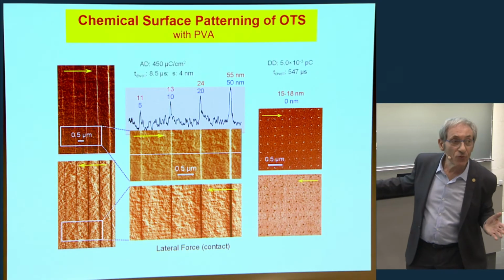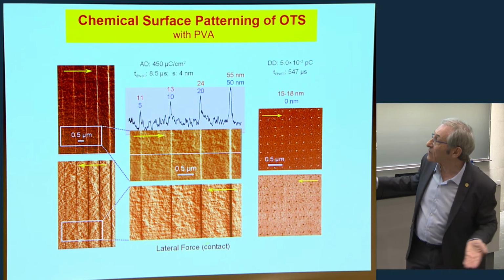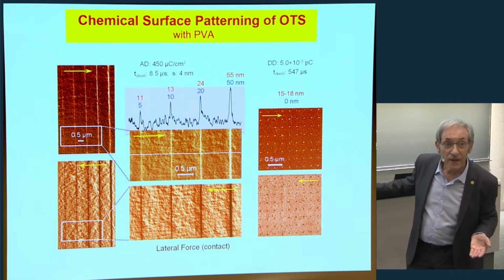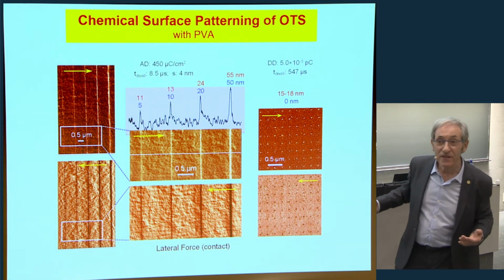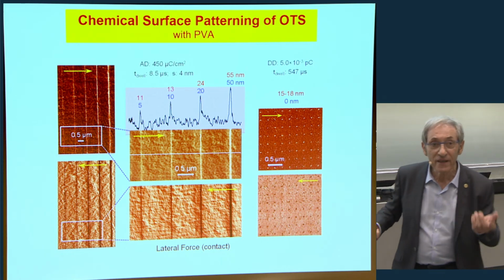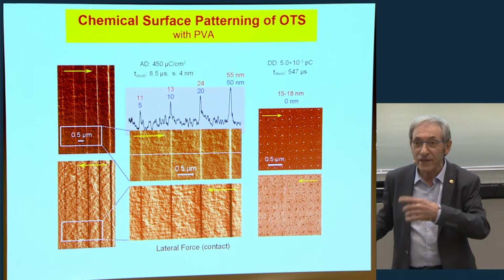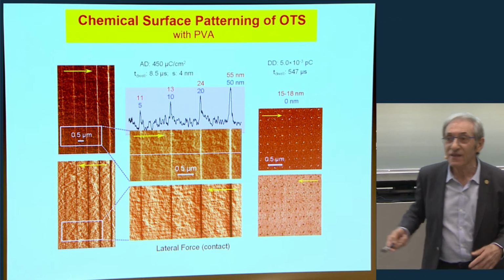Okay, we can do anything we want. We can make lines, we can make dots, different widths, and we can go to about 10 nanometers according to AFM. Maybe we have better resolution, but the AFM now competes with the electron beam in the resolution.